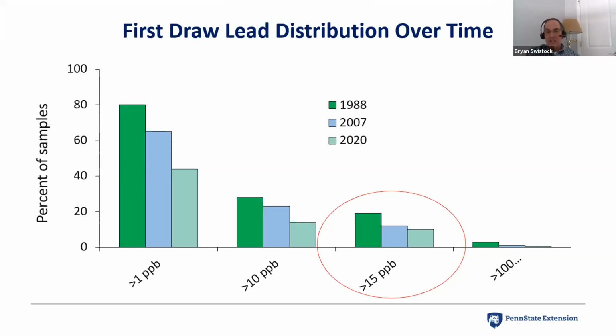If you look out there at the action level at 15 parts per billion, it was almost 20% in 1988 that were above the action level. In 2007, we dropped it down to 12%. The most recent data, we're down to about 9% now.